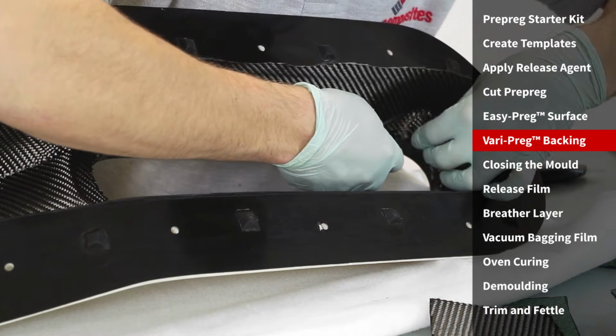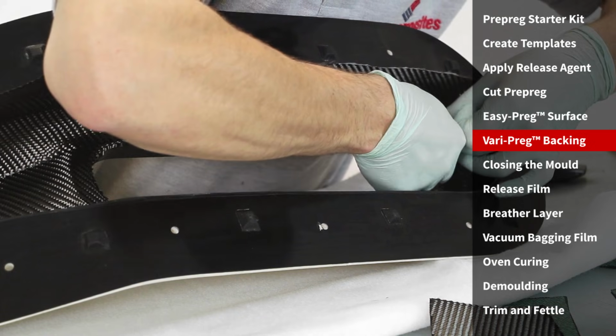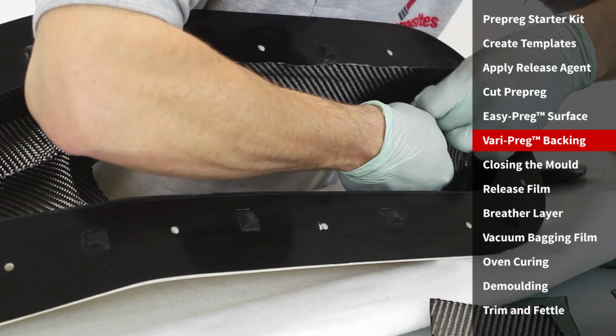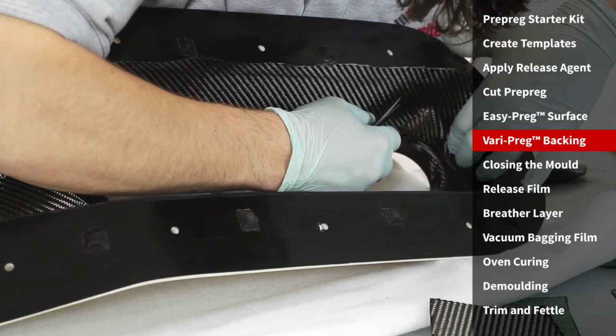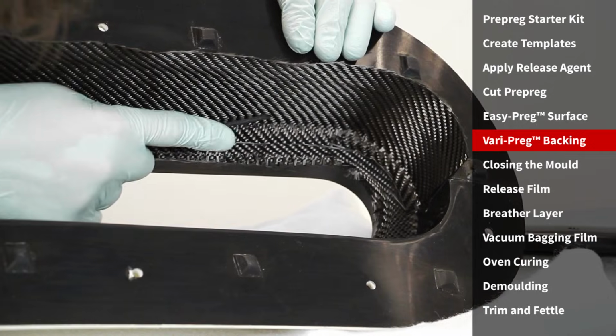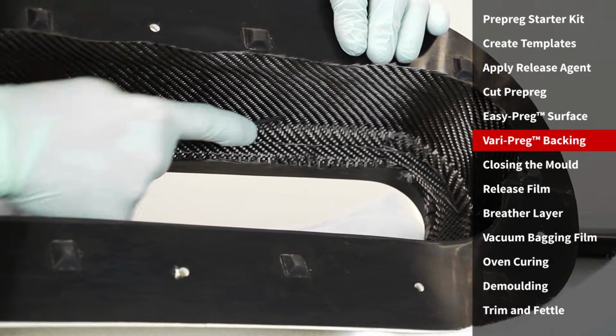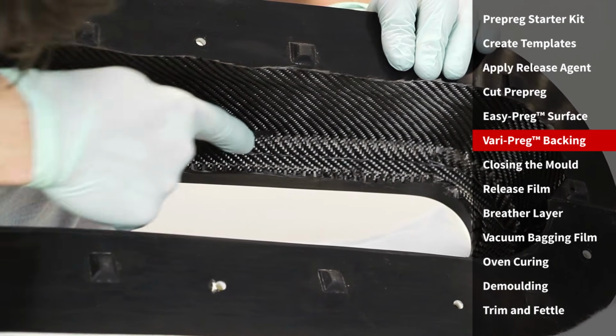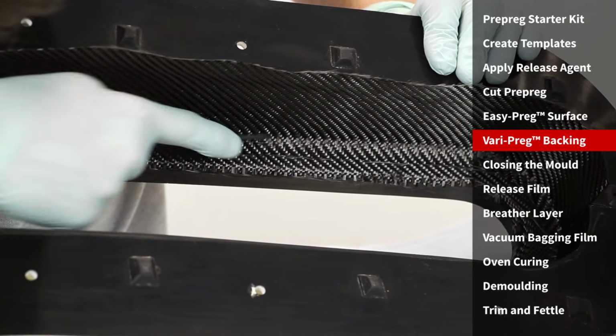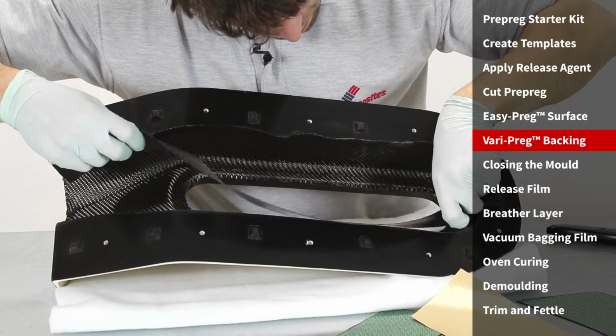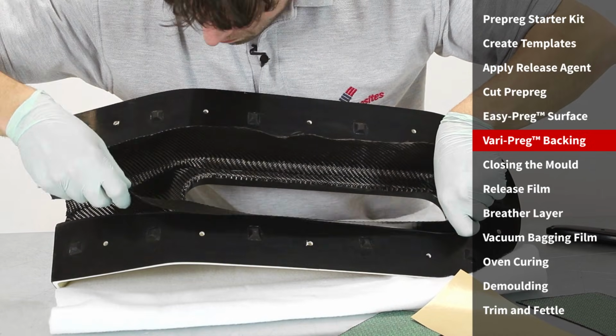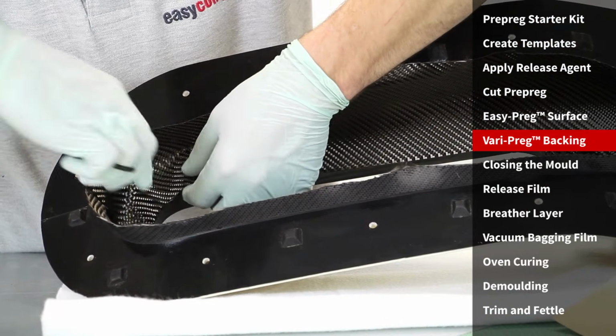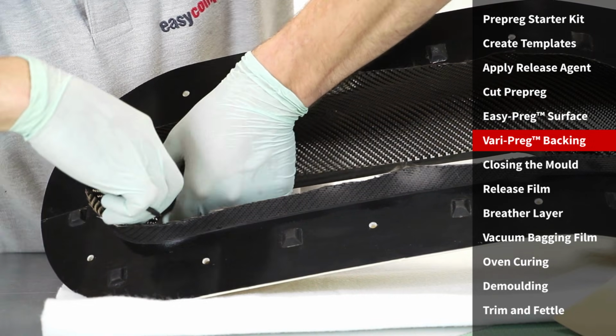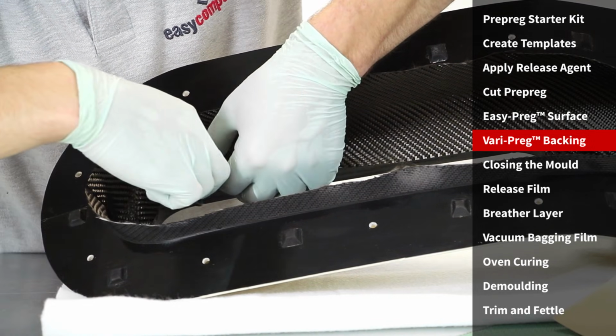To make the layup easier in the corners, I'm snipping small nicks into the material. I'm only doing this where the material is overlapping, so that it won't excessively weaken the part or be visible on the surface. Again, here I'm using the same Pre-preg laminating tool mentioned earlier to ensure that this special surfacing Pre-preg is pressed down firmly against the mould surface. Small snips are used again in the corners to allow the material to be folded into the mould with minimal distortion.